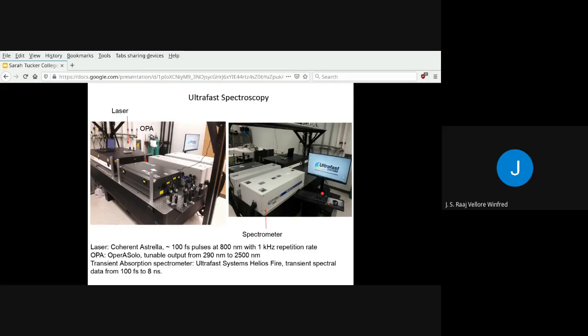This is a setup that I have in my lab. We have the laser that is shown here in this figure. This is a Coherent ultrafast laser. It is capable of producing pulses of 100 femtosecond pulse width at 800 nanometer peak wavelength. It has a repetition rate of about 1 kilohertz, which means that it can produce 1,000 pulses within 1 second.